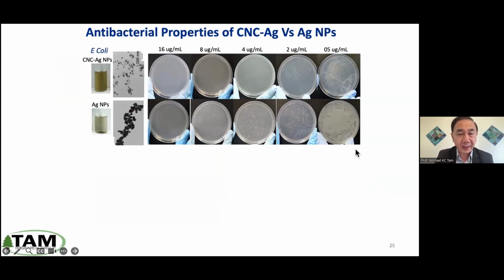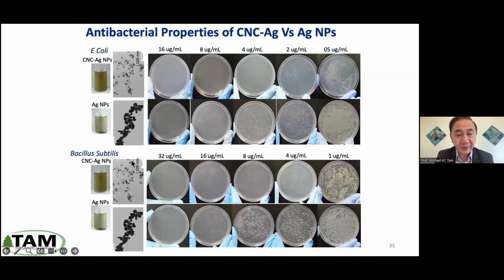Then we do a bacterial test. So this is the gram negative. With the CNC, as you can see, with silver nanoparticle, we have very good performance, 4 times better. We need 4 times less of the material to reduce the bacteria in the plate count. The same result for gram positive. So with this CNC system, we can reduce the amount by 4 times. It's more effective because of higher surface area.